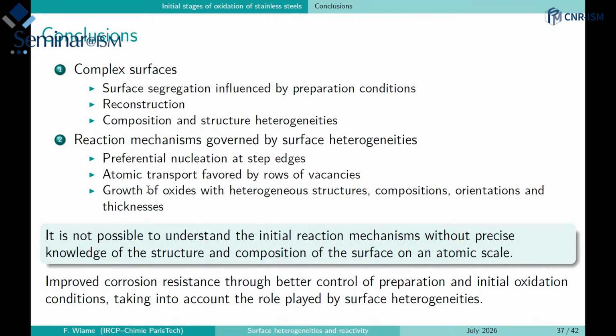So if we conclude, I showed you that the surface is much more complex than what most of the corrosionists think it is. In fact, the surface is reconstructed. There are many heterogeneities, although it's an ideal surface, let's say, the single crystal surface. So obviously, you can imagine on the real surface that we have many more defects and many more heterogeneities that should be taken into account if you want to understand the corrosion mechanism. And we have seen also that there is some preferential nucleation and atomic transport, which are favored by these heterogeneities at the surface. So clearly it is not possible to understand the initial reaction on the surface if you are not taking into account these very important heterogeneities, in composition and structure, at the surface. So the idea is to find out how we can improve this.